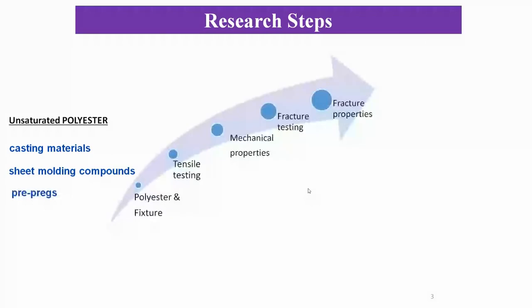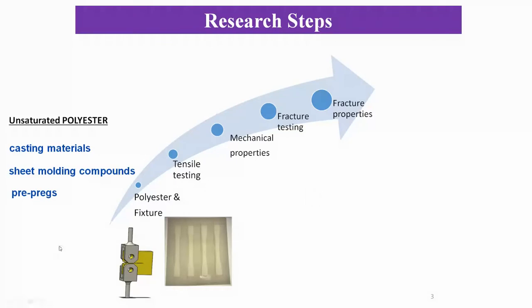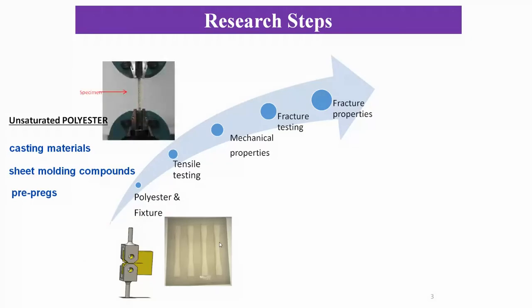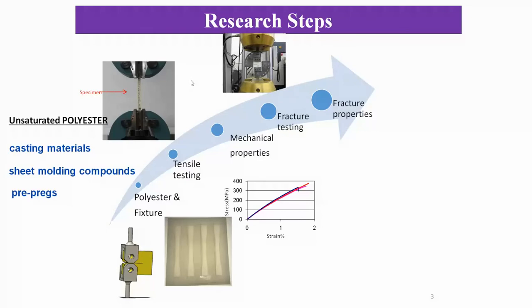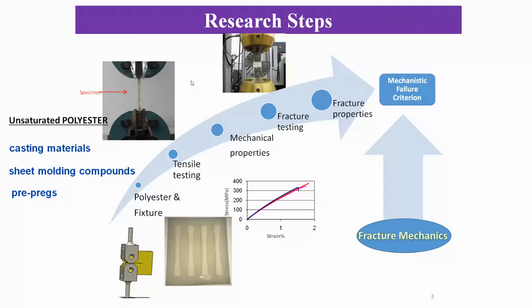To study this material, we follow this process. The mode 1 fixture is designed and manufactured. The tensile testing specimens are made using silicone molds matching the ASTM standard. The specimens are then tested under tensile testing to measure their mechanical properties, to be used later for the calculation of fracture properties. To study the fracture response of these materials, fracture testing of polyester is performed using the data and concepts from fracture mechanics, plus the fracture mechanics failure model. We aim to predict fracture properties of the composite made of this polymer.